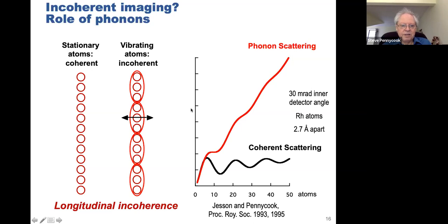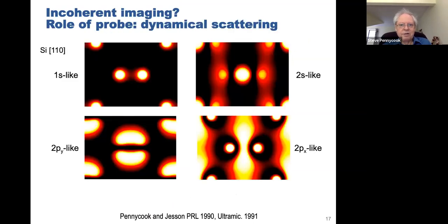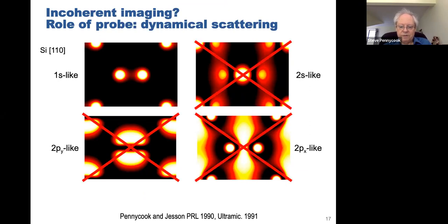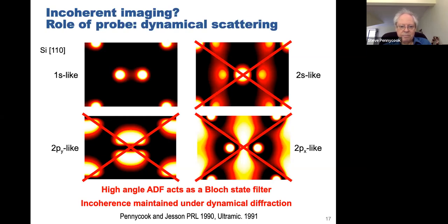Well, there's one other factor to consider, and that's dynamical diffraction. And we also figured out that in HREM, for example, the silicon fringes change with thickness primarily because of the interference between these Bloch states, the 1s and the 2s. And that really explains the thickness dependence and contrast reversals. But if you're looking at it with a high angle annular detector, only the intensity near the atoms matters, and the other Bloch states effectively are filtered out, don't contribute to the image. And that kind of nicely explains why incoherence is maintained under dynamical diffraction.